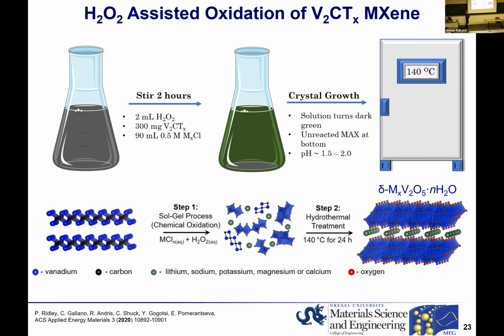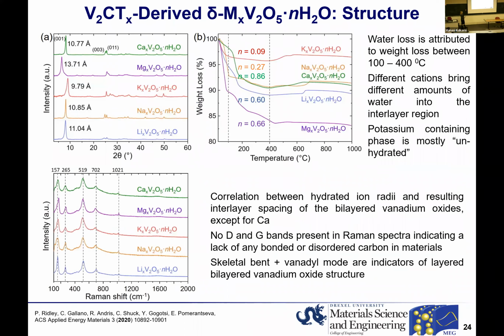And another change that we were able to achieve is that we were able to decrease the hydrothermal treatment temperature, which is 220 in the case of the alpha V2O5 precursor. And in the case of MXenes, we only needed 140 C to convert the vanadium carbide into the bilayered vanadium oxide. So we analyzed all the products. So again, the XRD patterns tell us that the interlayer spacing changes depending on the nature of the chemically pre-intercalated ion.